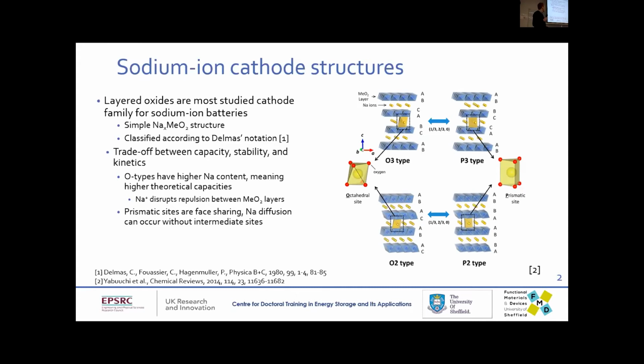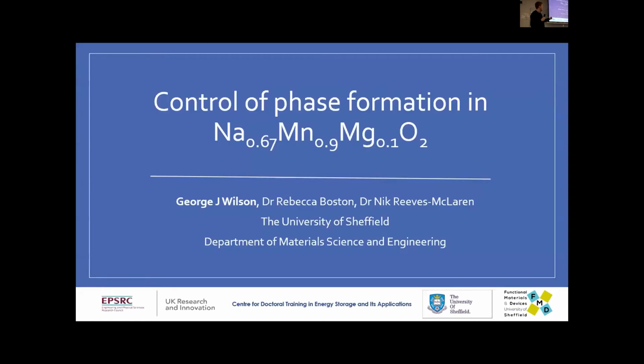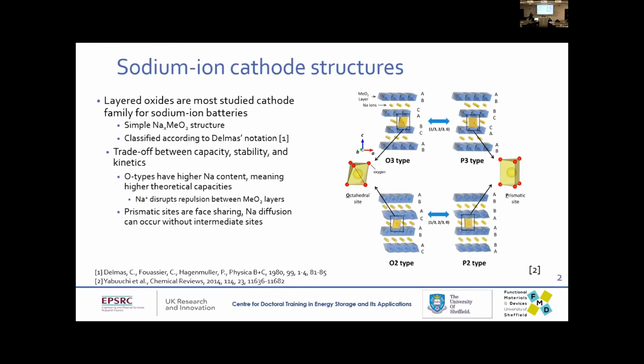In general, the layered oxides have this NaxMeO2 structure, and it's this value of x that determines whether it's an octahedral or prismatic site that the sodium sits in. Because I'm worried it'll go over a lot of people's heads, I will just say that if it's a high sodium content, so x higher than 0.9, or low, so lower than about a third, it'll be an octahedral site. And if it's at some intermediate value, like here where I've got x equals 2/3, then it'll be in a prismatic site.